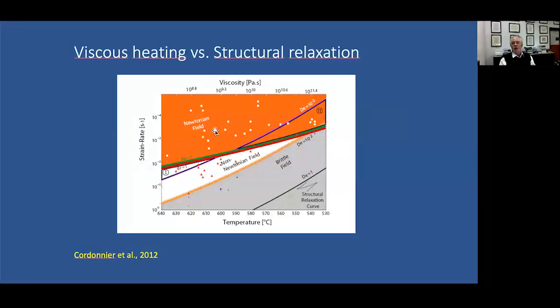And these two effects overlap. You can see two lines here which cross. One of the lines corresponds to the fragmentation of the sample. This is the purple line. The other line corresponds to the onset of viscous heating, which will push us away from fragmentation. And this temperature range is approximately the temperature range where these domes are cooling as they're on top of the mountain. So there's a prodigious complexity, which is potential in the materials engineering of these volcanic systems. It's wonderful for us to be able to understand the intricacies of the system, but it's a great challenge to understanding the behavior of these systems in a sense of civil protection.